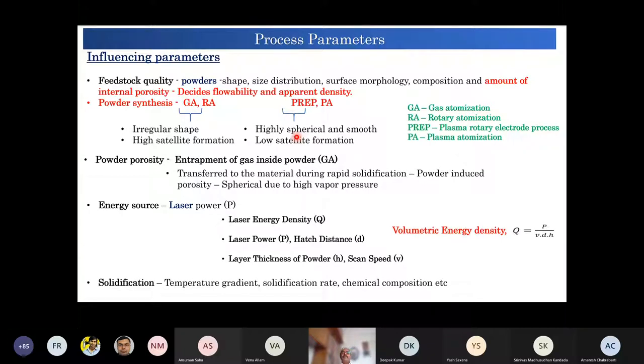And where are the limitations? Because to make powders from all the materials is very difficult. So one of the important process parameters, or influencing process parameters, is powder stock. So feedstock quality, that includes powder shape, size distribution, surface morphology, composition, amount of internal porosity. All these factors decide flowability and apparent density. And we need fully dense material for any engineering application.